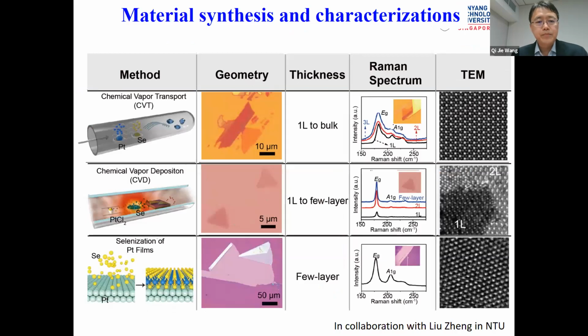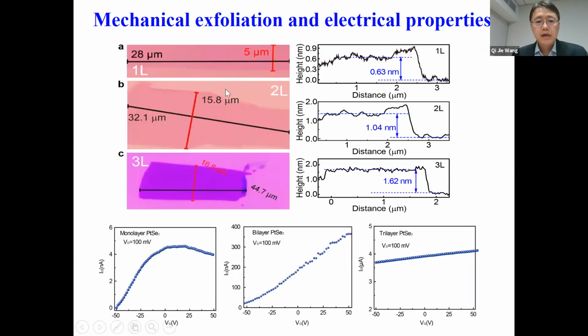We collaborated with Liu Zheng's group in the material science department. By using different fabrication methods, we fabricated relatively high quality material. We found that the so-called chemical vapor transport technology produces the best quality among the different methods. Then we fabricated devices with different layer thicknesses, verified by AFM.